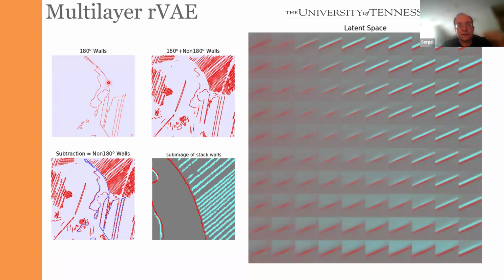Now, in this case, we can create an autoencoder which uses the 180-degree domain walls as one channel and non-180-degree domain walls as a different channel. So we're trying to learn the joint behavior of 180 and non-180-degree domain walls. And then when we formed the latent representation like this, we thought, okay, what does it even mean? It's absolutely not obvious. But it turns out that if you spend a little bit of time and think about the physics of the system that you study, this type of thing is actually relatively straightforward to understand.